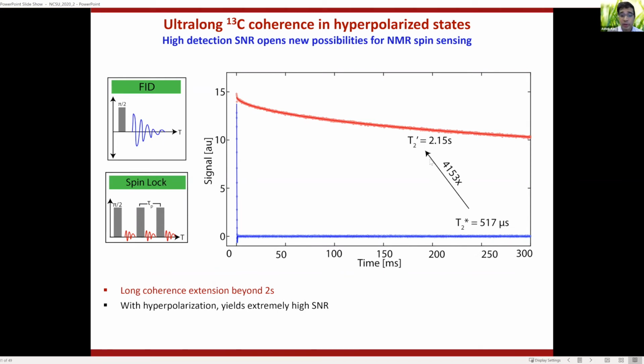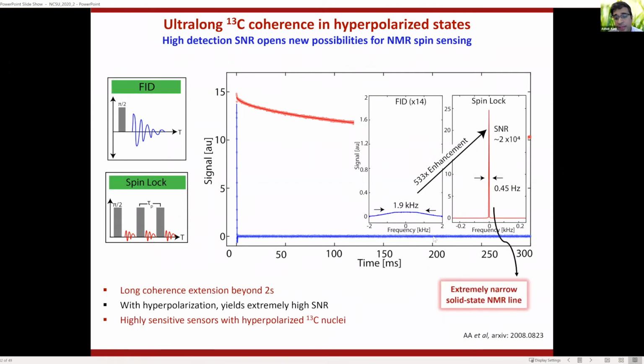So it turns out now if you do a full, and this is a one-shot signal, so there's no averaging here. This is the kind of signal that you get in 10 seconds of optical pumping, so very high signal. If you do a Fourier transform of this, the blue line gives you the old spectrum, which was hyperpolarized, which was very nice, and which we were very proud of for a long time. But now that's blown up about 10 times. But this is the new signal that you're able to get as a result of this protocol. It has two advantages. One, you get very large enhancement in signal because you can collect the signal for this 10-second period instead of 1 millisecond period. But you also get a very large line narrowing because the spins are inherently very coherent and you can hold them for a very long time.